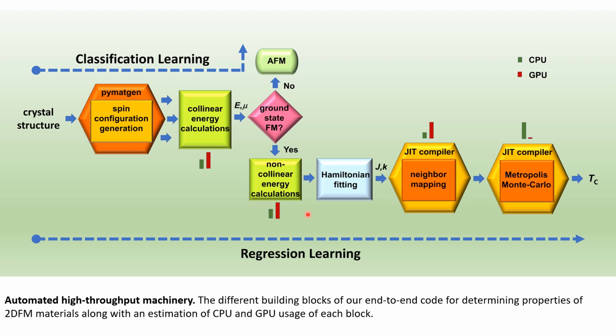So all of this data actually helps us to do a model fitting. What we use here is called an anisotropic Heisenberg model. You probably remember the Mermin-Wagner restriction. Under the Mermin-Wagner restriction, 2D magnetism cannot exist in 2D using the isotropic Heisenberg model. But we use the anisotropic Heisenberg Hamiltonian here, which takes into account the anisotropy as well as the exchange. So from these energy calculations we have enough data to fit the model Hamiltonian, and from this model Hamiltonian we get two kinds of parameters. One is J and one is K. J being the exchange parameters, which are obtained from the collinear energy calculations, and K are the anisotropy constants, which are obtained from the non-collinear energy calculations.